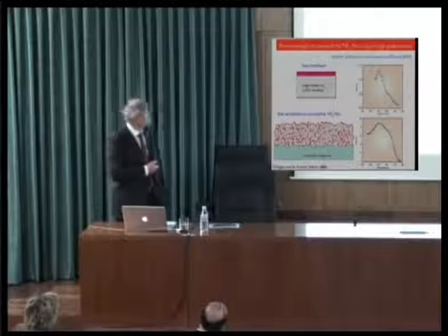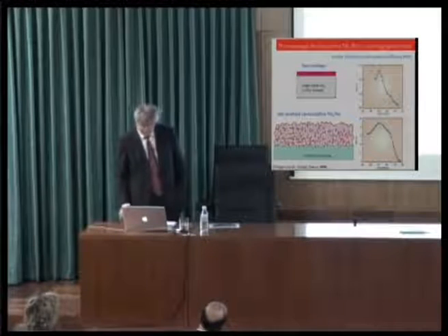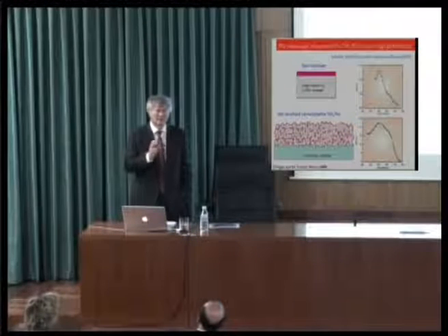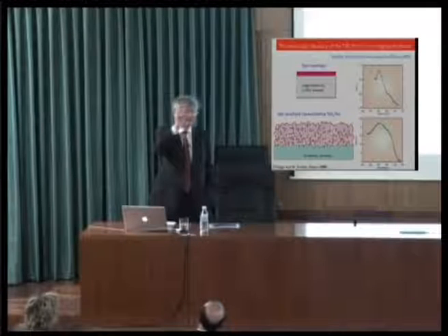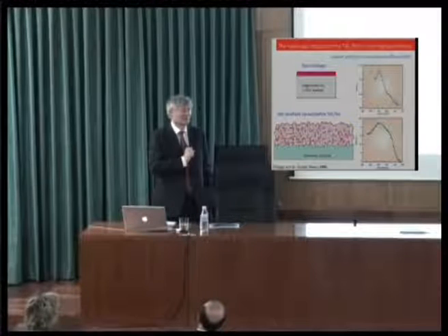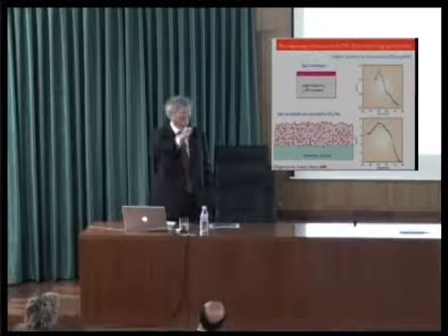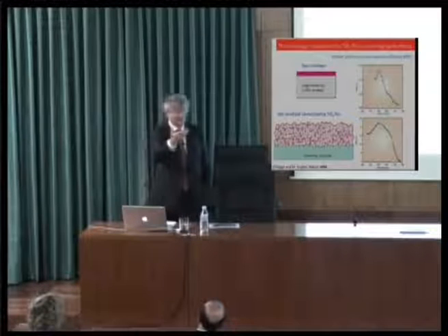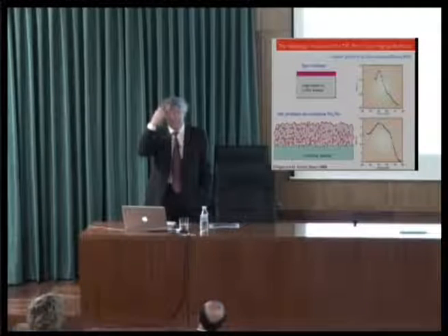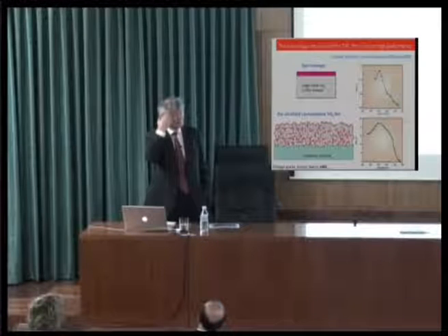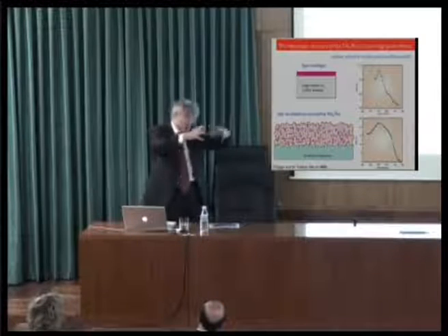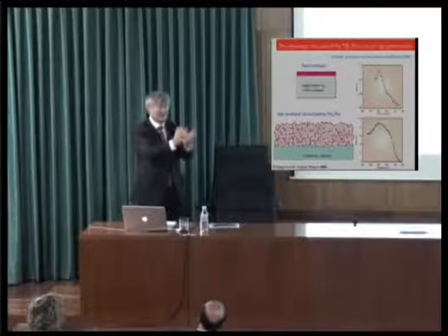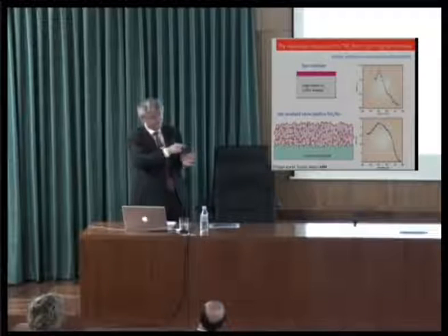Well, the fact is, if you take that message home, then I think that's very important. The fact is that electrons and holes are not moving in the same material. Electrons move in the oxide, and the holes move in whatever you use in a porous space. And so, of course, they would love to recombine. They love to recombine, but you can control this. The dye itself is an insulator, and so it sits right at the interface. If the electron wants to go back out, it has to cross the dye molecule.